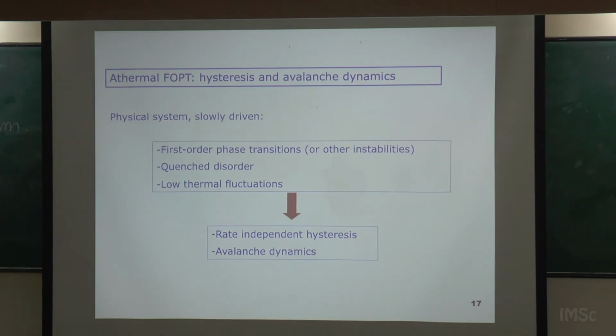So this is a sort of summary. When do we expect avalanches? We need a first-order phase transition. I think that this can be generalized to other problems, and this condition here can be changed to: we need a certain instability. And I think that just generalizing phase transitions to instabilities, we can even take this scenario and put fracture and other questions here. Okay, but this is more something to be discussed. We need disorder. Generally, we say quenched disorder, but even if the disorder is not quenched, things will be more complex, but we need disorder. And we need low thermal to athermal conditions, low thermal fluctuation.